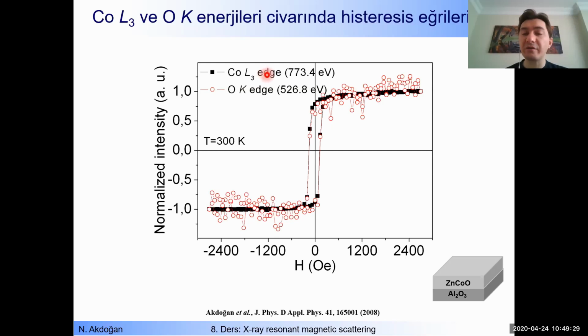So this also supports that conclusion: cobalt sits on the zinc site in the zinc oxide lattice and makes bonding with oxygen. So oxygen is magnetic due to the neighboring cobalt atoms. This is a very nice property, and as I told you, no other method can give you that information. XRMS is a very, very powerful method to investigate magnetic properties of materials element specifically. So with that, I finish my lecture.